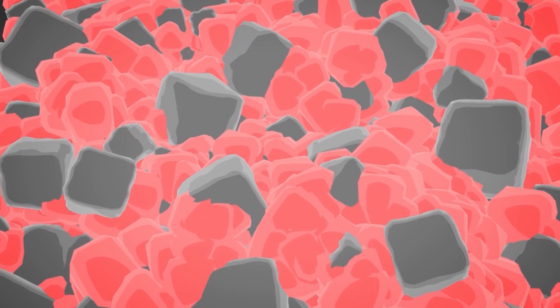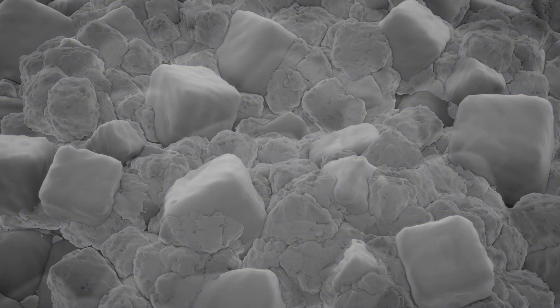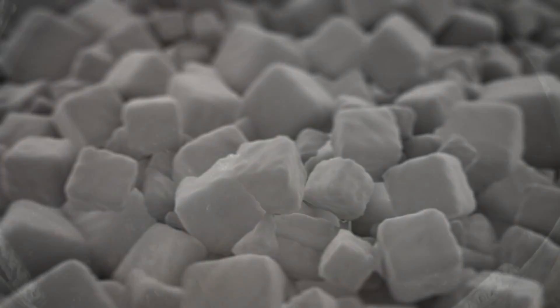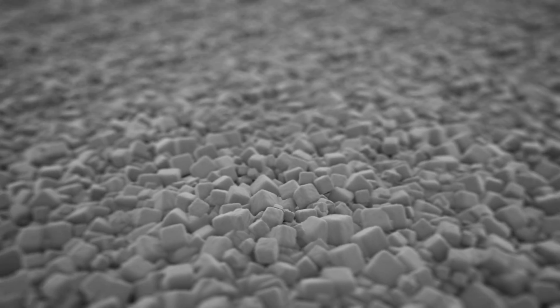KNT Group specialists have solved this problem by using a novel manufacturing technique. Zeolite extrudates are formed using a temporary binder, which disintegrates in a specially prepared solution, allowing new crystals to grow and combine with each other, thus producing granules that consist entirely of synthetic zeolite.